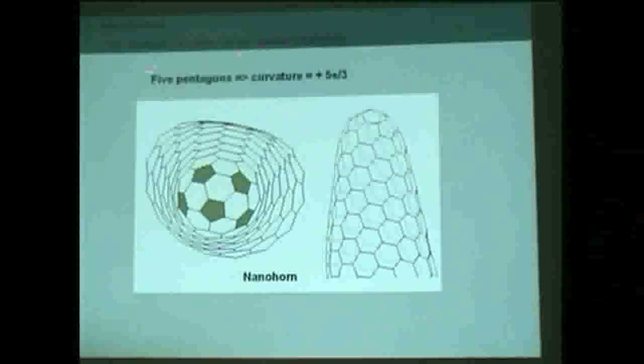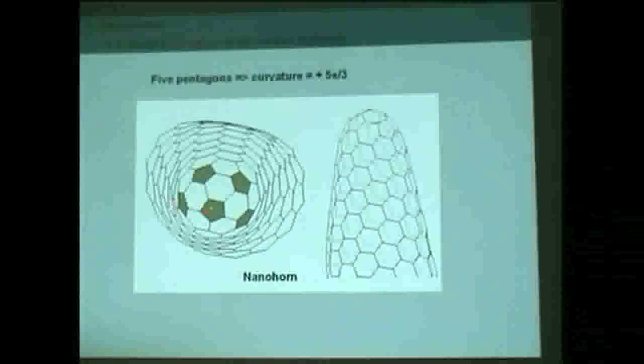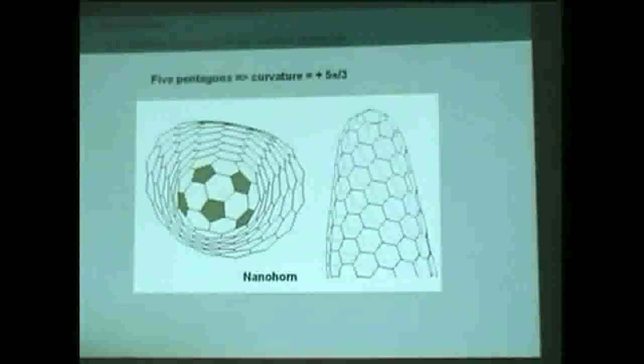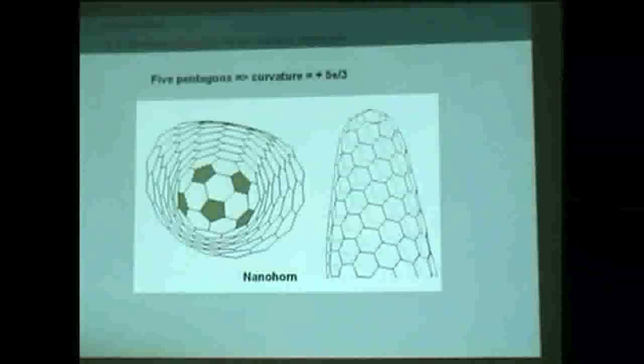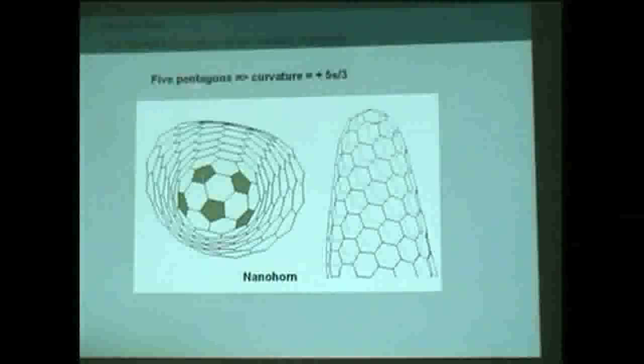So this is another example of a structure called a nanohorn, where there are 5 pentagons, 1, 2, 3, 4, 5. In this case, the curve is not completely closed. It's not like we have 12 pentagons. It's not like it's half closed. It's something a bit less than half closed. You still have a shape at the end which looks like a cone, which is conical. This is another example, and the curvature is 5 times pi over 3 because we've got 5 pentagons.